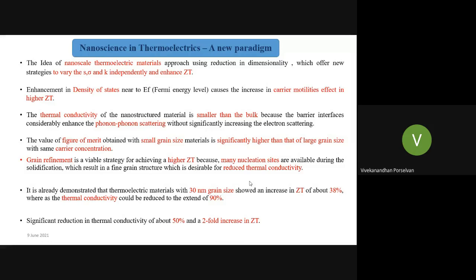But the thing is, whenever we are providing the nanostructure phenomena, we are increasing the resistance to thermal conductivity by sacrificing some kind of electrical conductivity. So the nanoscale does favors in terms of thermal conductivity, and it will have a detrimental effect in terms of electrical conductivity. So thereby we have to trade off between that, and we have to make it in such a way that we increase the electrical conductivity, at the same time have a very low thermal conductivity. That is why we are doing a lot of strategies. That means doing the doping, making the nanostructuring, doing the alloying process, doing the nanocomposite process, like that.